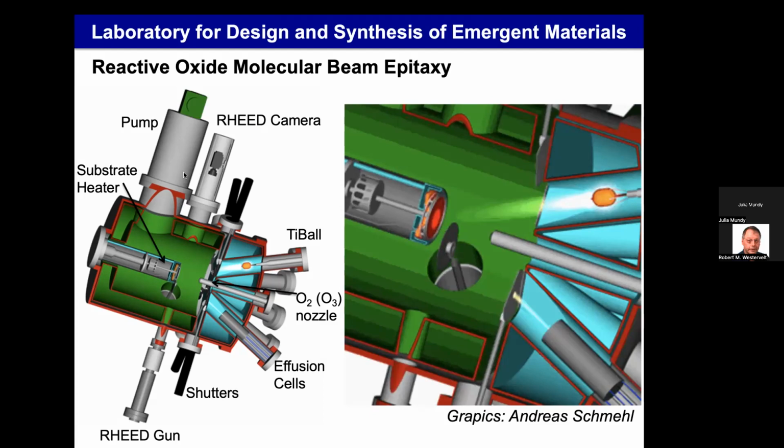And we do this all in an environment of oxygen, so that's just the oxygen that's coming in here. And in some cases, we actually do it with ozone, O3, which is extremely reactive. It allows us to oxidize compounds that are not readily reactive. So this is that. So here we have a spot here. This is a heater, so we can also heat our template.